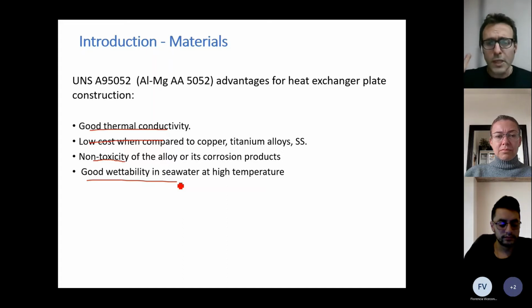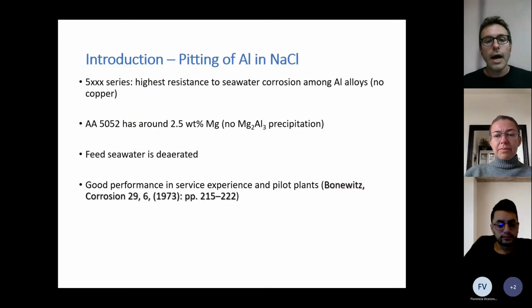Because this film of distillate and brine must be stable, right? So this aluminum fulfilled all those requirements. And there were also some favorable papers that said, considering different aluminum alloys, it had the highest resistance to seawater corrosion, especially because it has no copper. Like aluminum, it doesn't like copper in terms of corrosion.